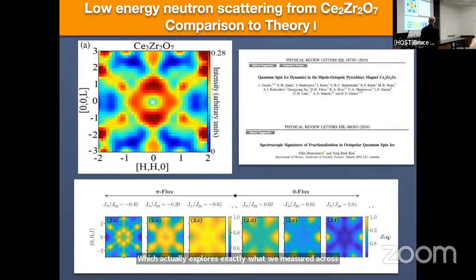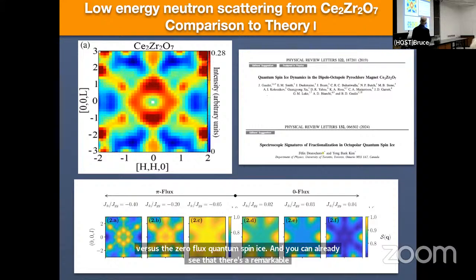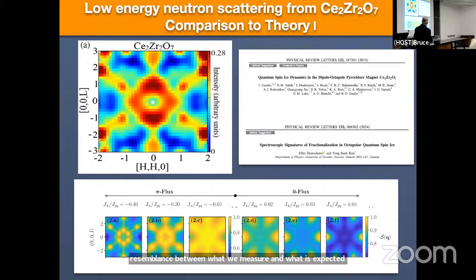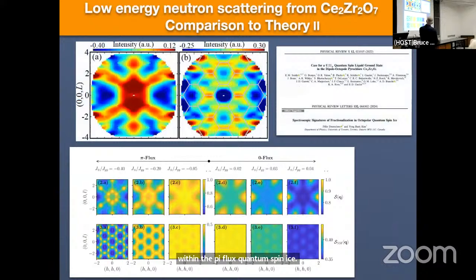And what I'm showing you is expectations for this structure factor in the pi flux quantum spin ice versus the zero flux quantum spin ice. And you can already see that there's a remarkable resemblance between what we measure and what is expected within the pi flux quantum spin ice. Okay. And actually, they go further than that.